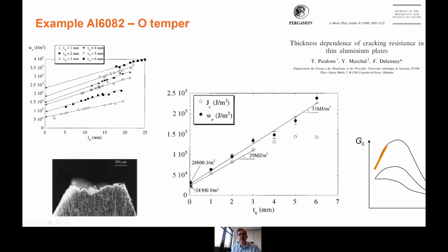And what you find immediately is that the constant term in the regression, so the essential work of fracture, clearly increases with thickness, and this is seen now in the big graph in the center, where you see as black dots the essential work of fracture values as a function of thickness, and you see that the essential work of fracture increases linearly with thickness. So we really are in the left-hand side regime of evolution of fracture toughness with thickness.